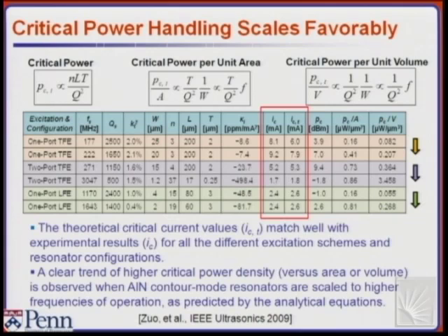So going to a higher frequency, even per unit volume, is independent of thickness, right? So per unit volume, you really have a net gain in going to higher frequency in terms of power handling of the device. People might think that's counterintuitive, but actually scaling and going to higher frequency is advantageous in terms of power handling. And that's demonstrated experimentally also, so it's confirmed.